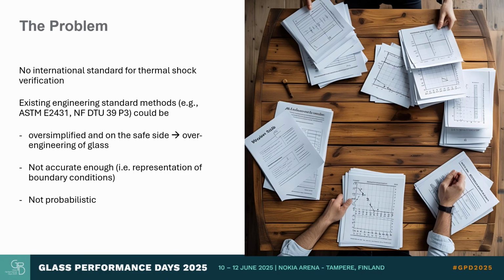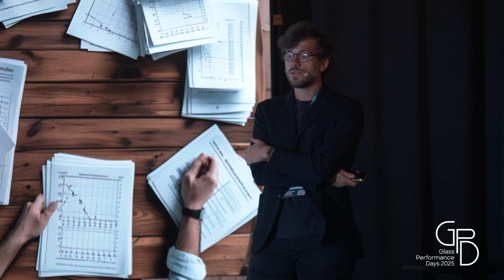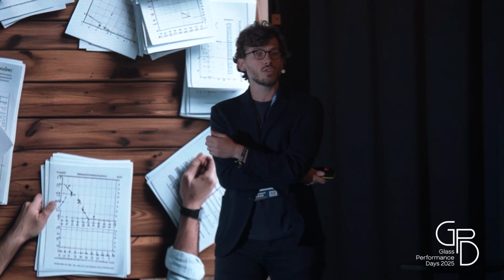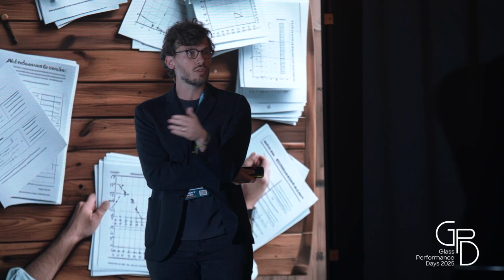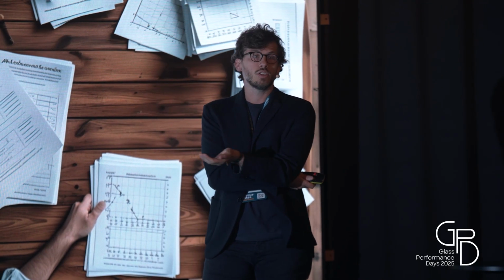The problem is that there are no internationally recognized standards to do a thermal shock risk assessment. There are some existing methodologies in national standards: the French DTU 39 P3 for IGUs and the ASTM only for laminated glass. These methods can sometimes be oversimplified, which means that maybe we are over-engineering the glass and strengthening it unnecessarily. The question is whether these are accurate enough. Do they give a good enough representation of the boundary condition that we have from the climate? And they are not probabilistic.